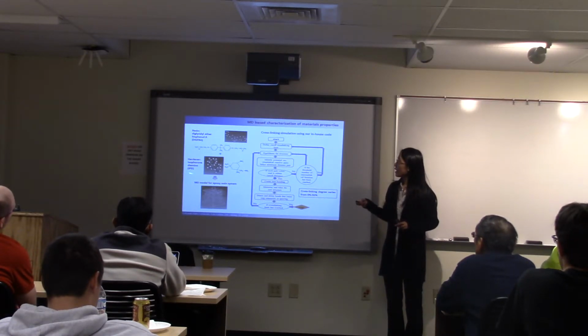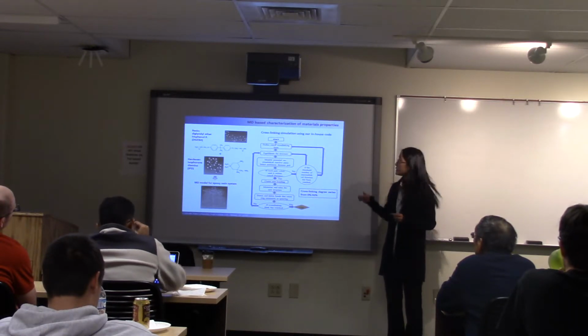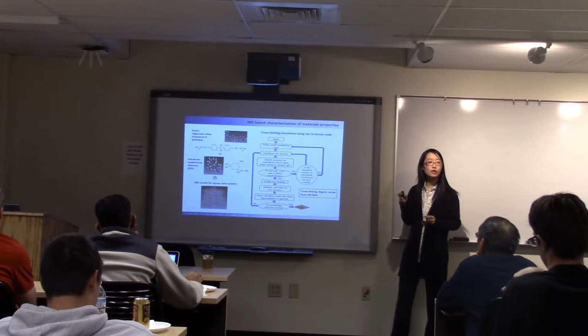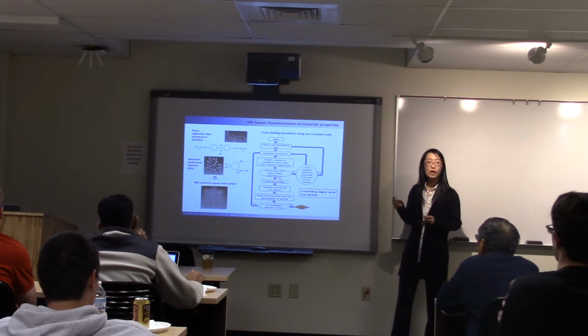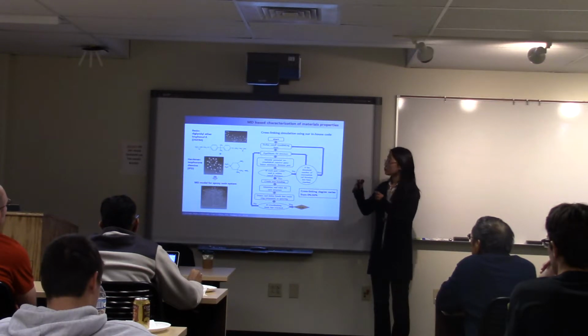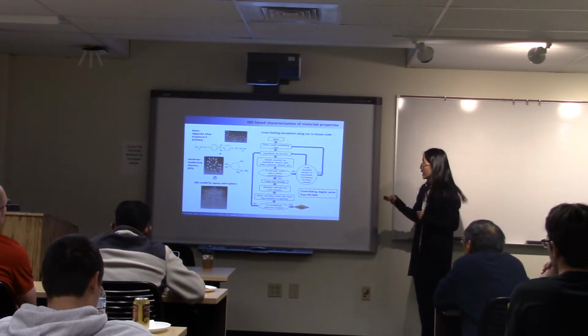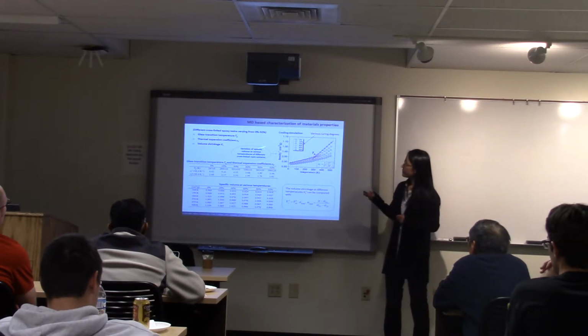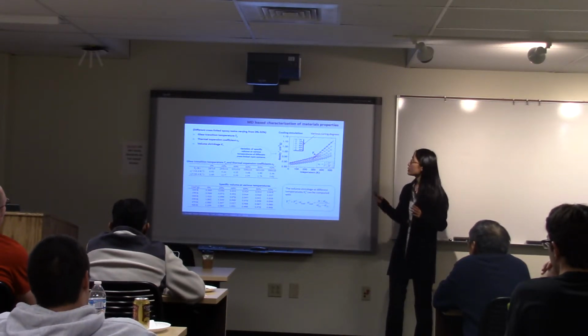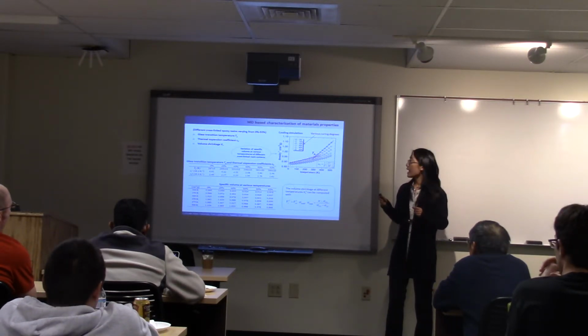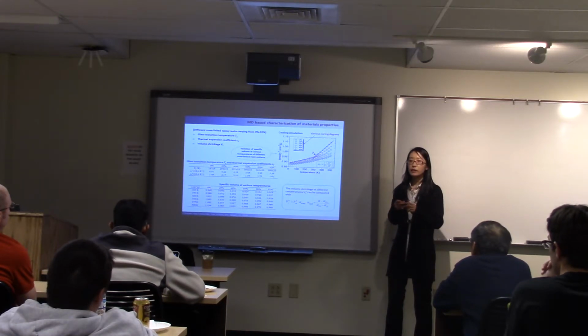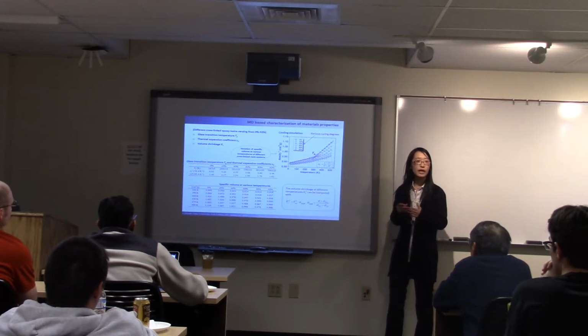The epoxy resin system we chose is composed of DGEBA and IPD, which is a commonly used industrial epoxy resin system. We need to create cross-linking degrees varying from 0% to 92%, which is very close to the experimental value. We have an in-house code to create bonds between the epoxy ring and the amine, that is, to create bonds between these two reactive sites in order to create the different cross-linking degrees. We conducted MD simulation to characterize the mechanical properties and see their change with time and cross-linking degree. Because their dependence on pressure is relatively low, we didn't consider pressure as an influencing factor.